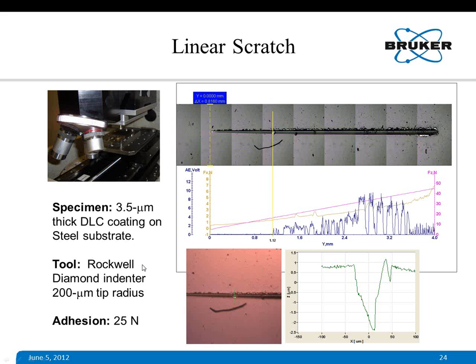A Rockwell indenter is used for this scratch test, with a progressive load, that is, a linearly increasing load, and it actually started from the very beginning. There are several failure modes on this particular coating with this Rockwell indenter.